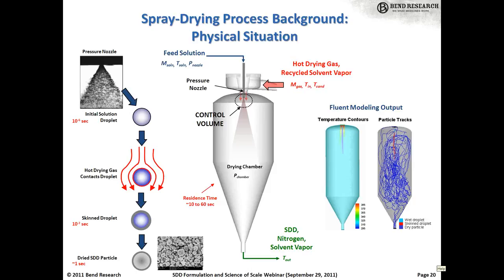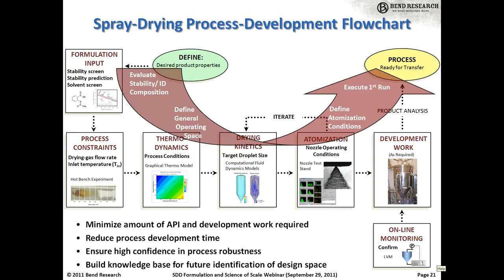On the right here, we're showing another computational fluid dynamics model output with a user-defined function that models the individual droplet drying so that you can actually trace droplet drying from the wet droplet through the skinned phase where it still may be sticky, and then into the final dried SDD particle. So we've shown here also on this slide a number of the key spray drying process parameters, and there are quite a few of them. So how do you begin to identify your initial process conditions? So moving on to the next slide, we've developed a methodology for doing that initial process identification. Over the years at Bend Research, we've been lucky enough to have developed spray drying processes for hundreds of SDDs.